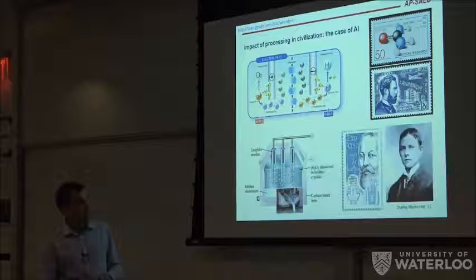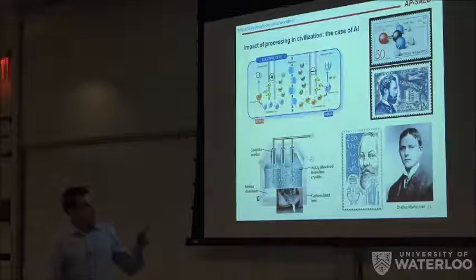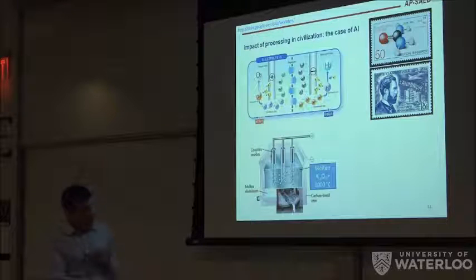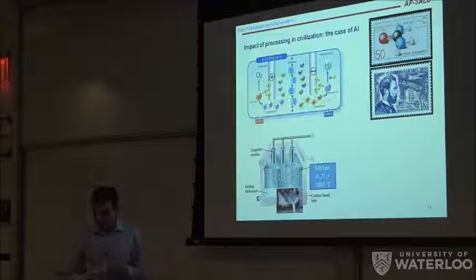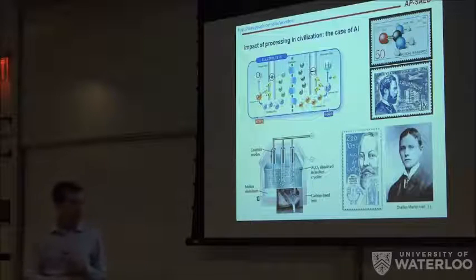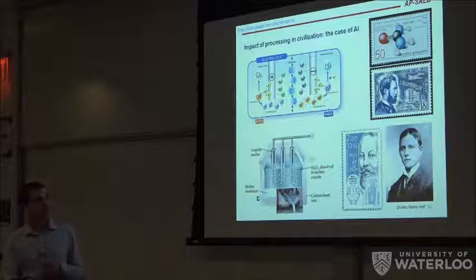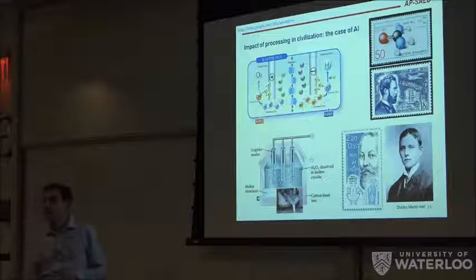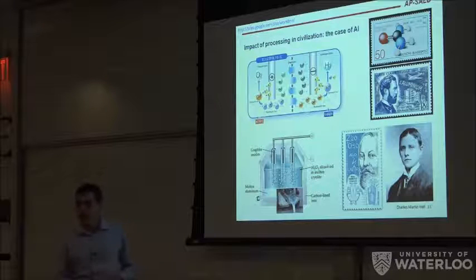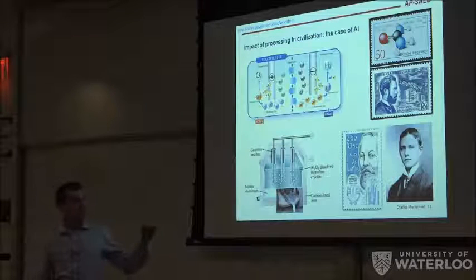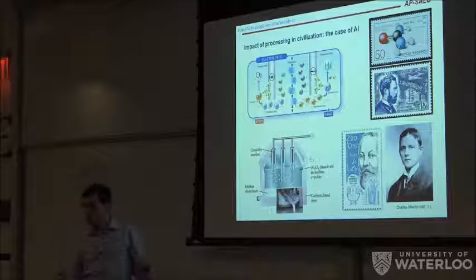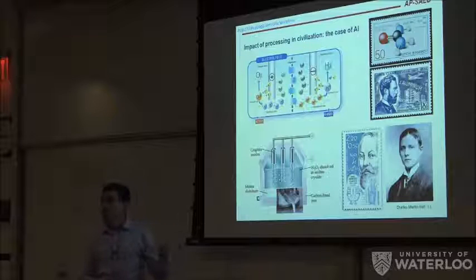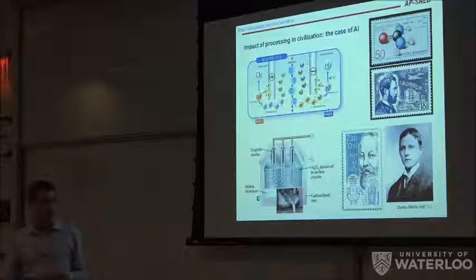and he's also well remembered. But even with this process, it would still not be viable to produce aluminum this way. So it was not until, again, Paul Héroult and Charles Hall in the United States discovered that you could dissolve aluminum oxide in cryolite, with sodium and fluorine, and then you could reduce the temperature of the process to below 1,000 degrees, and that made the process economically viable, and as important as it is today.